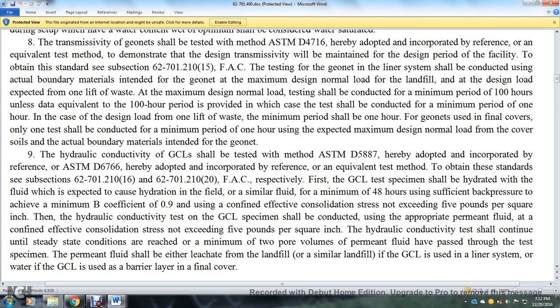9. The hydraulic conductivity of the GCLs should be tested with the method of ASTM D5887, hereby adopted and incorporated by reference, or ASTM D6766, hereby adopted and incorporated by reference, or an equivalent test method, to obtain the standard, subsections 62701 210 16 and 62701 210 20. F.A.C., respectively. First, the GCL testing specimen shall be hydrated with the fluid expected to cause the hydration, or a similar field fluid, for a minimum of 48 hours, with sufficient back pressure to achieve a minimum B coefficient of 0.9, with a confining effective consolidation stress not exceeding 5 pounds per square inch.